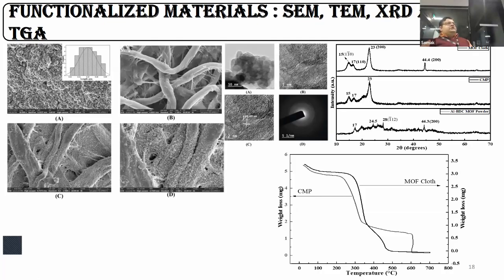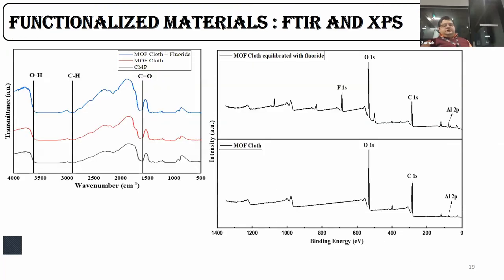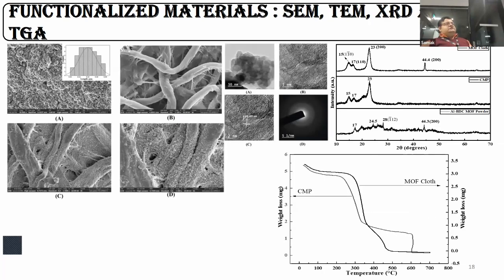In case of the TGA, that is the thermogravimetric analysis, we were able to see that the complete weight loss starts happening in a range from 400 to 700 degrees Celsius. But in case of the carboxymethylated filter paper, the weight loss is much faster. When we deposit the MOF cloth, because of its high resistance to heat, the degradation starts at a comparatively higher temperature.